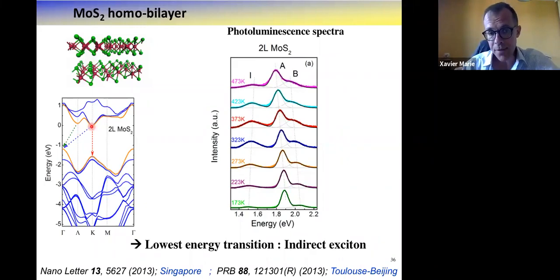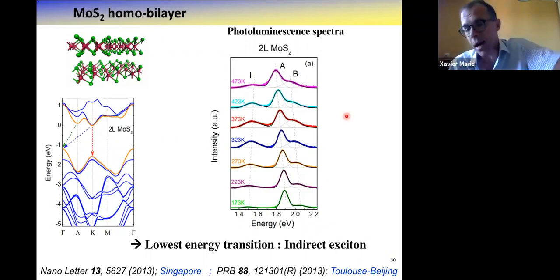But you still have this direct transition at higher energy. And indeed, when you do a photoluminescence spectrum, which was done now 7-8 years ago on bilayers, this is a curve from this paper from Singapore, you see photoluminescence intensity as a function of energy. So indeed, you evidence this indirect transition at low energy, but you evidence even in luminescence or in absorption the transition associated to the K transition, which keeps a strong oscillator strength. Indeed, it's at higher energy.